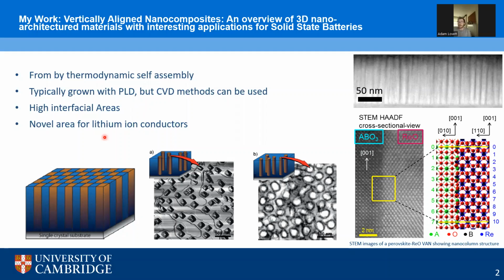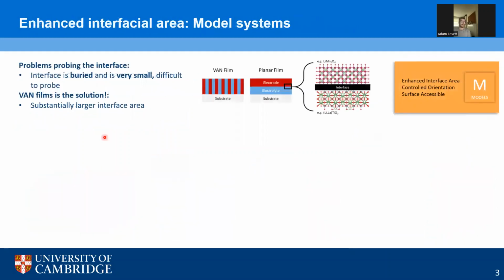So why might you want to study these materials? Well, firstly, you might use them as a model system to study battery interfaces. Why? Well, battery interfaces, solid-state interfaces are buried, and they're very small, which makes them incredibly difficult to probe. But VAN films offer a solution, really down to 2 reasons. The first being it's a substantially larger interfacial area due to being a 3D architecture. And this interface is also surface accessible, allowing techniques such as AFM to be used.